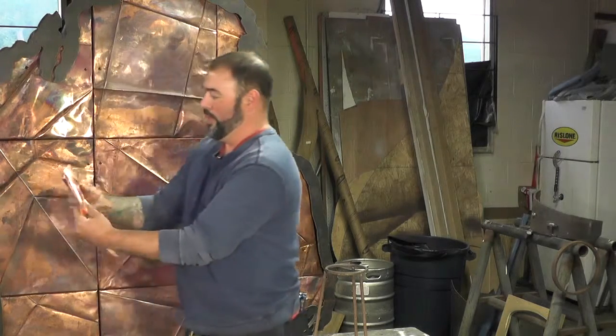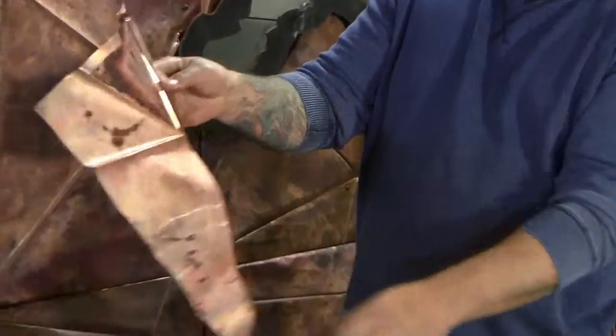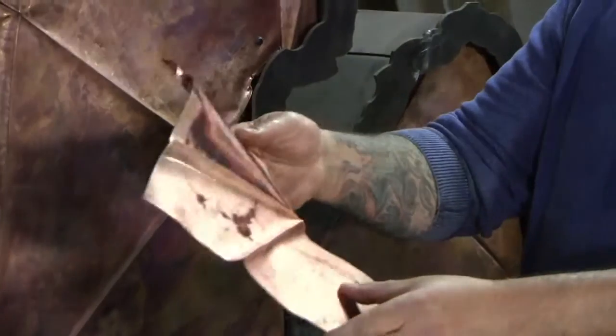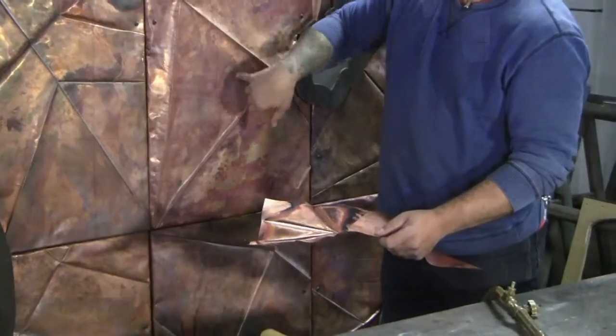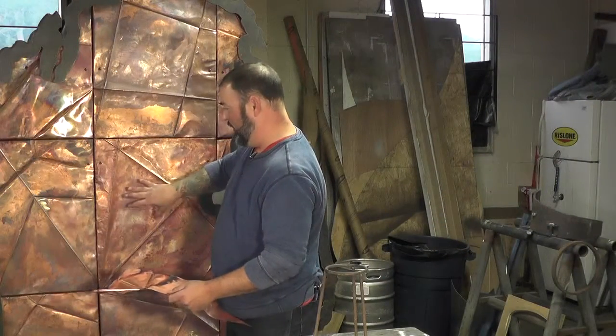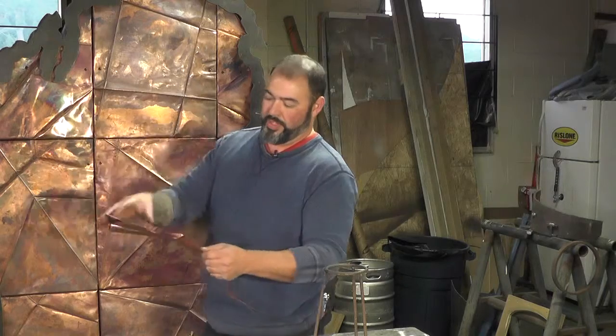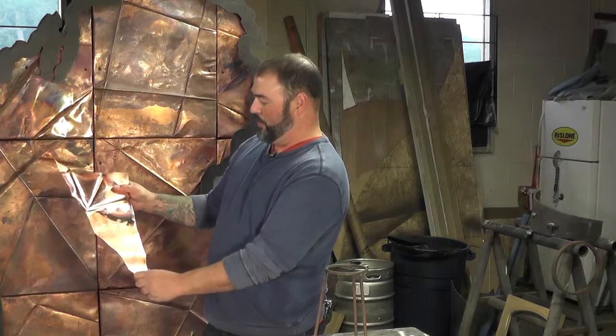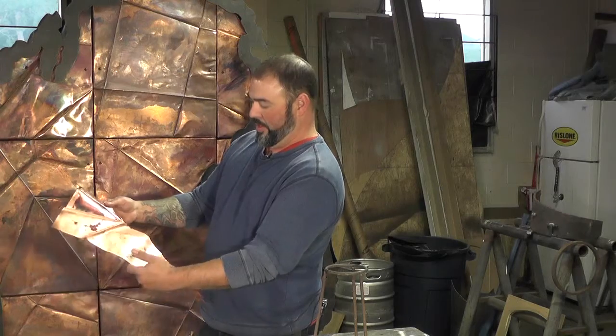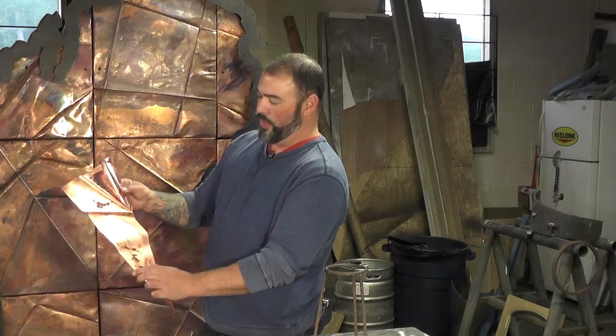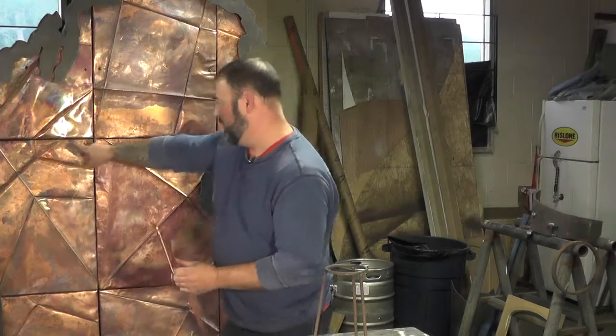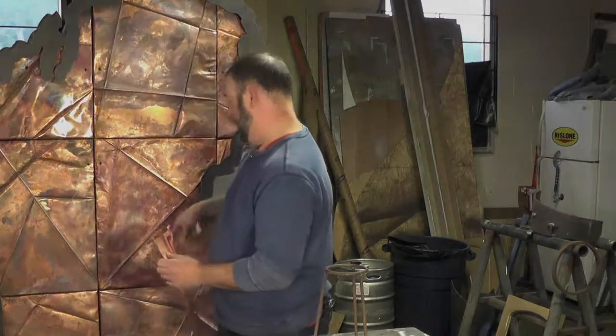You can see how dramatic these fold lines are and how interesting that changes just a corner of copper into a surface that's got some really dynamic qualities. You can also see I've got some of my hazing. There are textures in the patina here that you may or may not be able to see on the camera, from continual heating and quenching and heating and quenching. You don't get it with the first round, but you get some of the effects. After going back and reworking this a few more times, we'd eventually get this really dramatic effect that you see in some of these panels.